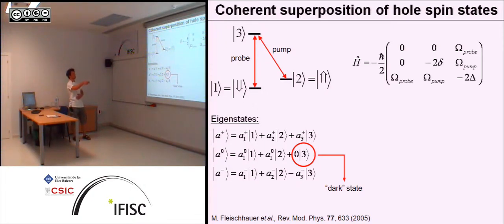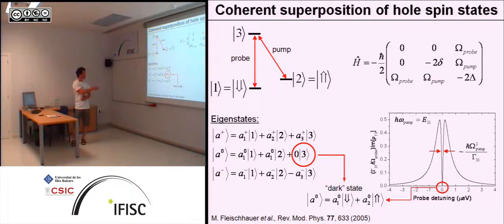If we again look at the Hamiltonian here, we have the three-level Hamiltonian of the system. And now the very interesting part is you can now look at the eigenstates, eigenvectors of this Hamiltonian. And you get these three new eigenvectors. I've eliminated the prefactors here. They basically depend on detuning and pump intensities and things like this. But the really important part is that the A0 eigenstate, the new one, doesn't have a probability of the third state. So that means it cannot couple to the optical field. So it's a dark state. While all these other states have contribution of the excited state. So these states can be coupled optically, but this one cannot.